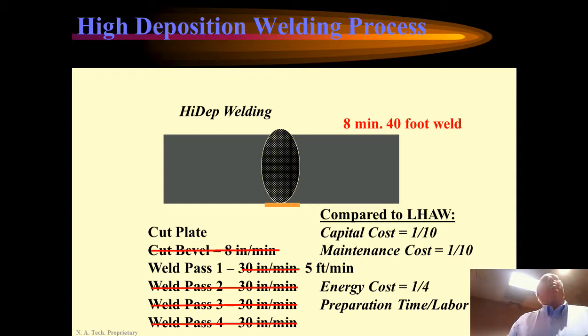Yes? Which part contributes more to the penetration of the weld? We've got some heat flow modeling that we've been doing, but I'm not sure we have all the answers for that yet. The arc probably does most of the work near the bottom of the joint, because induction is an electromagnetic field which dissipates as it goes down into the material. So it probably heats the joint a little more on the top, and the arc heats the material a little bit more on the bottom, but it's a very even heating from top to bottom.